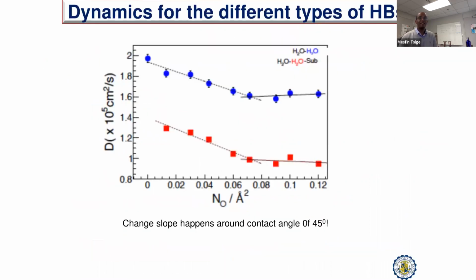The first thing that we have done is we looked at their diffusion coefficients, how the diffusion coefficient changes with the degree of oxidation. So in bulk, the diffusion coefficient is around 2. It's up in here. What we have observed is that all the interfacial water molecules move less than what they do in bulk. So there is a reduction in the diffusion coefficient. But there is also a difference between the three different kinds of water molecules. Those that are directly involved with hydrogen bonding with the substrate, they move slowly, they form and break. The others tend to move slightly faster.